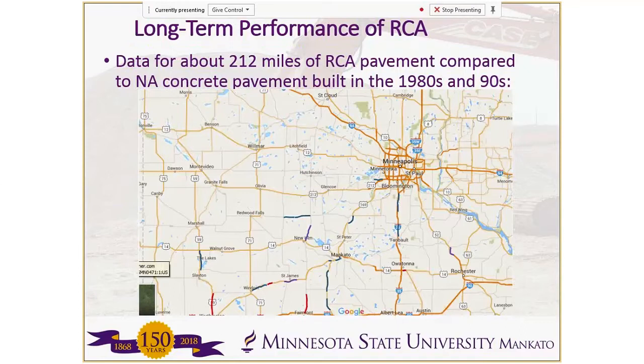So all these pavements that were built, we had a lot of them in Minnesota that were built in the 1980s and 90s. We wanted to look at how they performed, look at their long-term performance record, and compare it to similar concrete pavements that were built around the same time, because we know the specifications change from time to time, so we have to keep it within the same time period. And also we looked at the same range of traffic on the pavements as well. This is just a map showing in Minnesota the locations of those pavements with the RCA concrete. And there's about 212 miles of those pavements that were built.